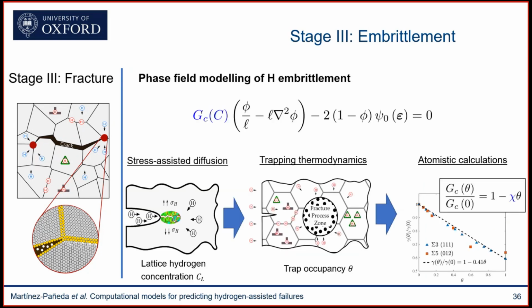Okay, so this is very easy to incorporate in the model, as you can imagine, because we are solving a multi-physics model, so we are solving for the hydrogen distribution within our sample. We can then use Oriani's trapping equilibrium to relate the hydrogen concentration to the trap occupancy in whatever interface we feel is relevant, like a grain boundary. And then we just need to go to this atomistic calculation and come here with our coverage and decide quantitatively how much we reduce the fracture energy. So everything can be naturally incorporated into the model.